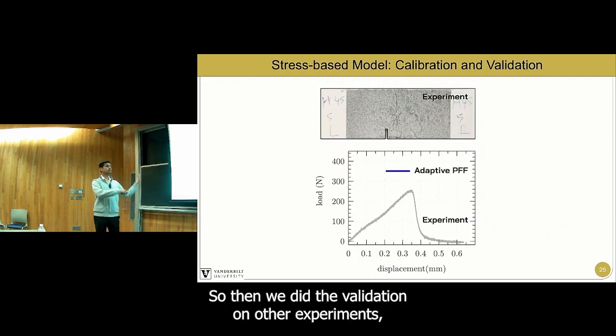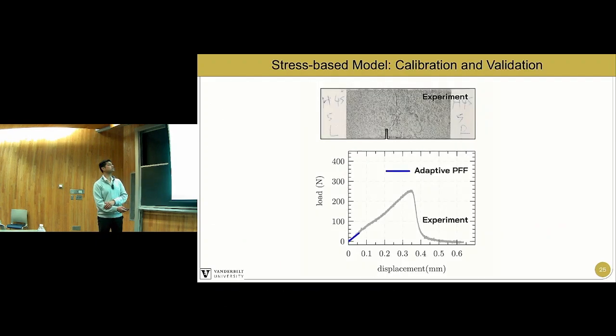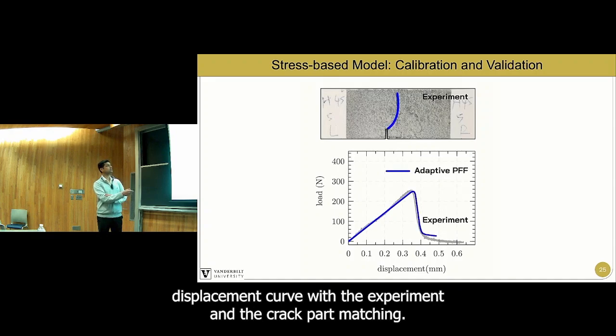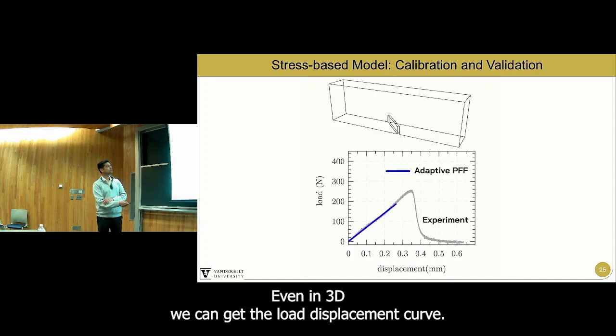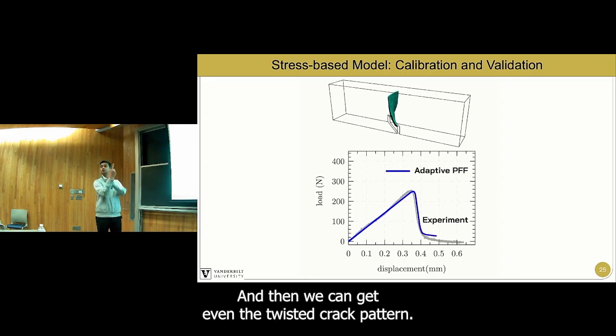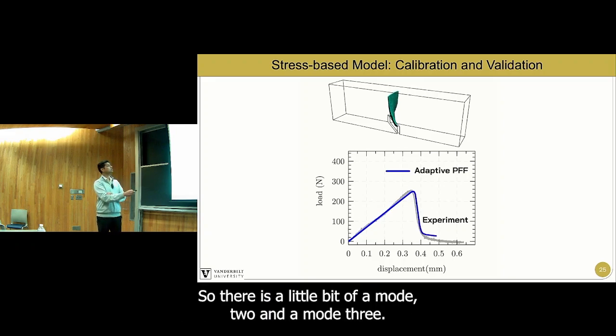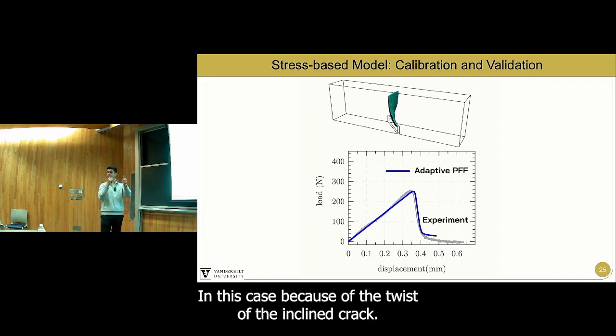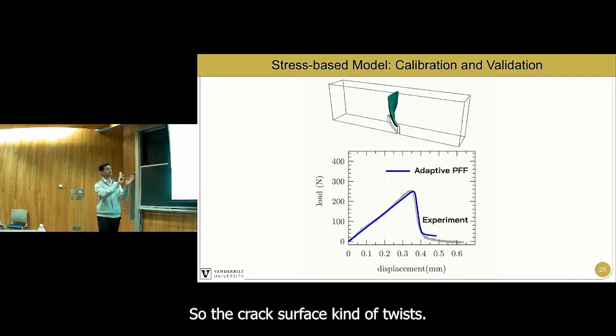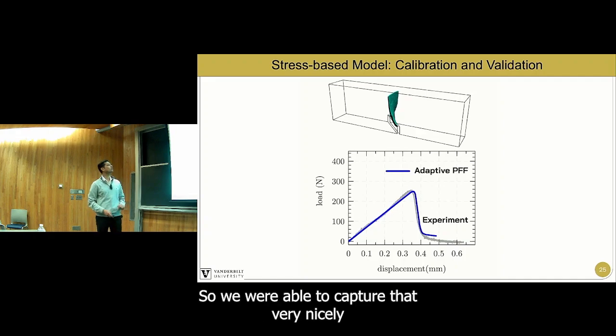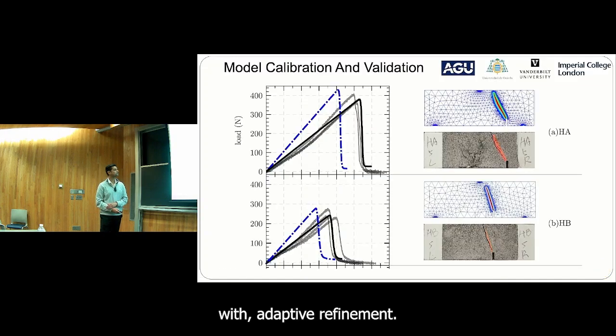So then we did the validation on other experiments, and we were able to get the load displacement curve with experiments and the crack path matching. Even in 3D, we can get the load displacement curve, and then we can get even the twisted crack pattern. So there is a little bit of a mode 2 and a mode 3 in this case because of the twist of the inclined crack. So the crack surface kind of twists. So we were able to capture that very nicely with adaptive refinement.